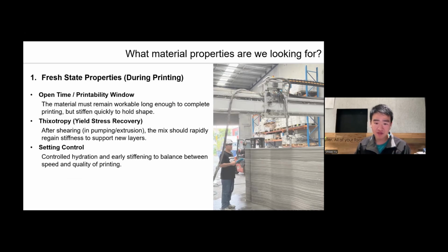The next property is thixotropy, or yield stress recovery. After the mix is sheared during the pumping process, it should quickly regain stiffness to support the next layers. There's been a lot of academic research into this, but for large-scale construction printing, the effect is actually not that significant. That's because the lag time between layers is usually long enough to gain strength, instead of relying on thixotropy. And finally, setting control. We need to manage hydration and early stiffening fast enough to keep the project moving, but not so fast that it may lead to cold joints between layers and pumping issues.